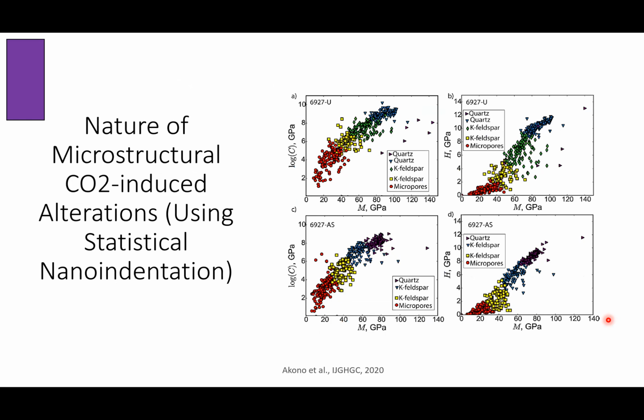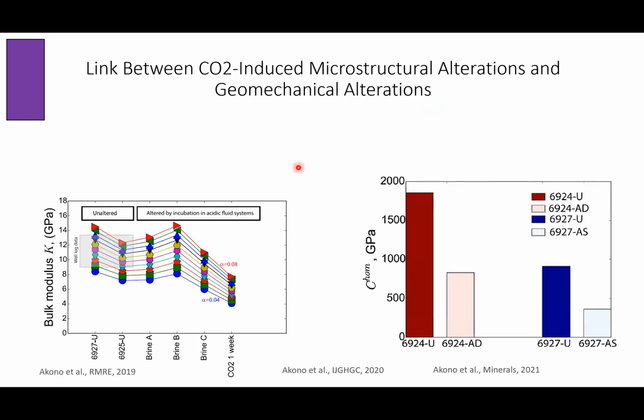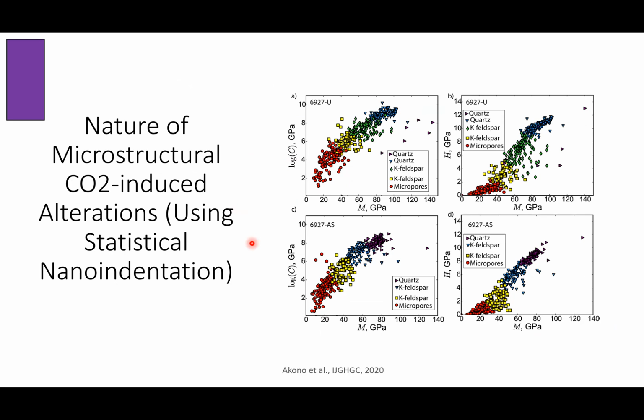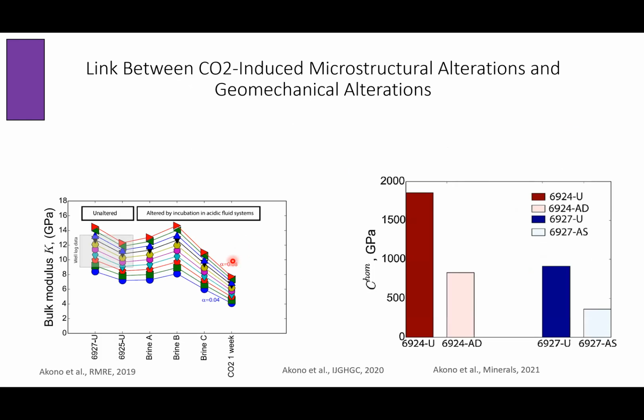And we can quantify it further. One thing that we were looking at is, when we look at the mechanical properties that are decreasing, what are the mechanical properties decreasing? So this is why we're really trying to use a different modality for depth-based nanoscale mechanical testing. So we looked at the indentation modulus, the indentation hardness, and we look also at the creep, so log creep behavior, so looking at time-dependent behavior, and the result was really the same. We have these decreases in the phases, but we also have decreases in the mechanical properties. So this is shown here. We have a decrease in the bulk modulus, but we also have a decrease in the creep modulus that occurs between unaltered and altered in both cases.